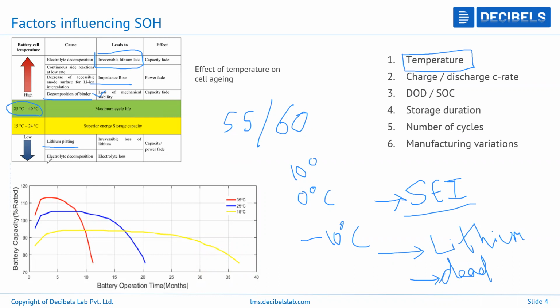Eventually your electrolytes will start to solidify and decompose. That is another dangerous situation, and it can cause what is called an internal short circuit. To prevent all that, it is recommended that the operating temperature is maintained within this range all the time. Of course, the same applies during storage. If you are keeping it not during operation but during storage, there are certain guides.